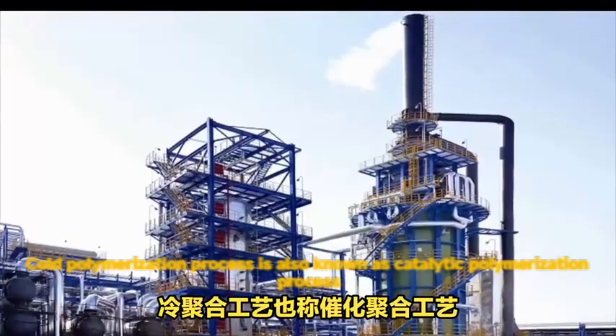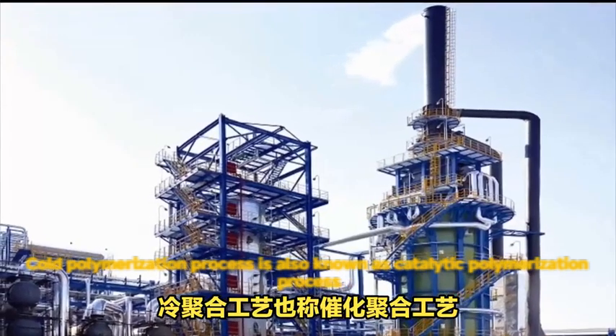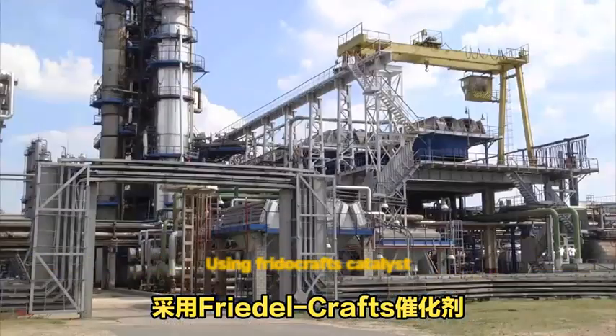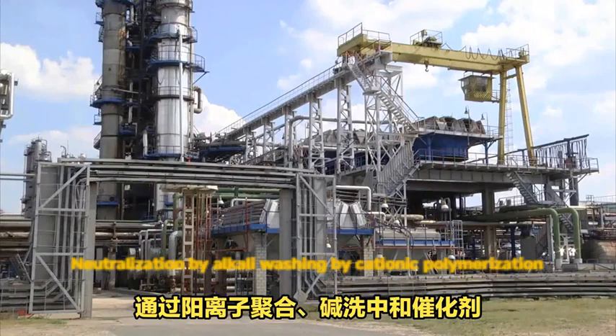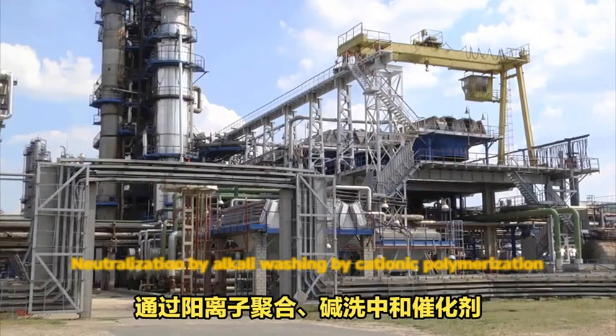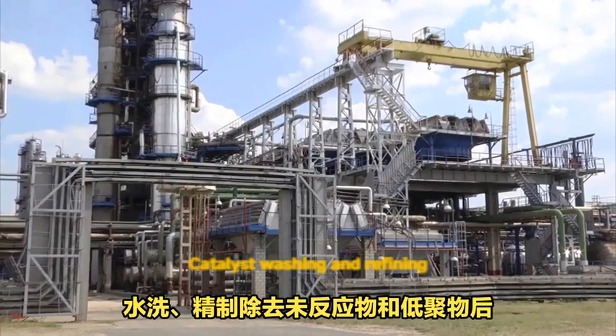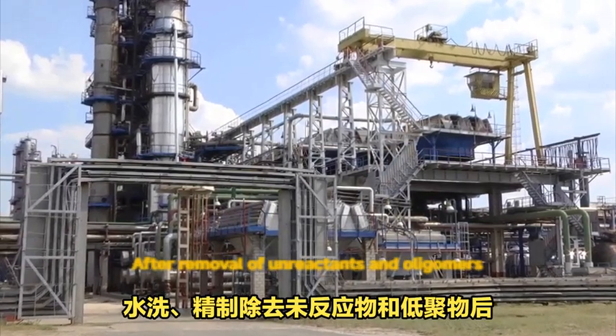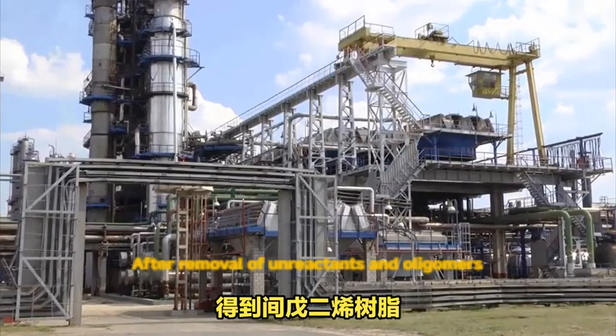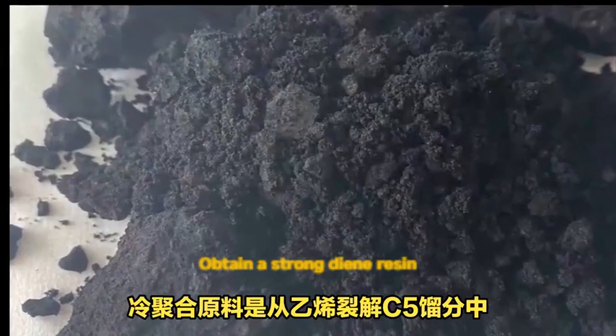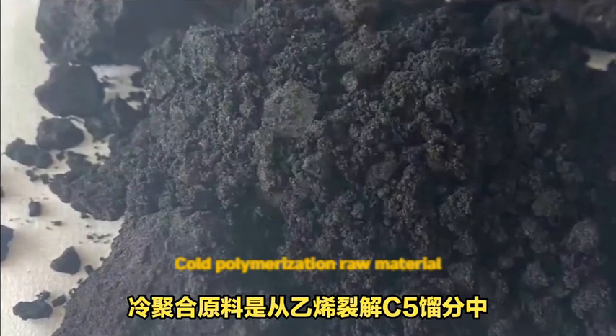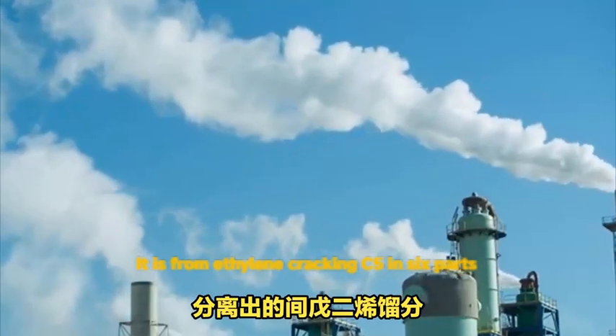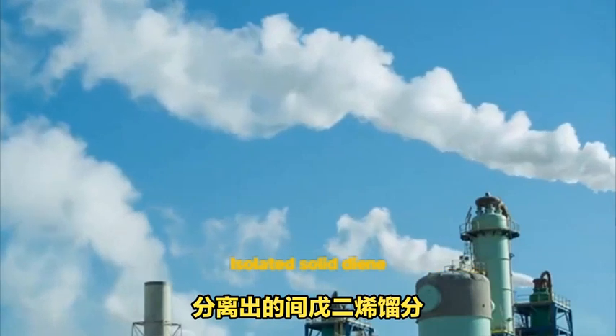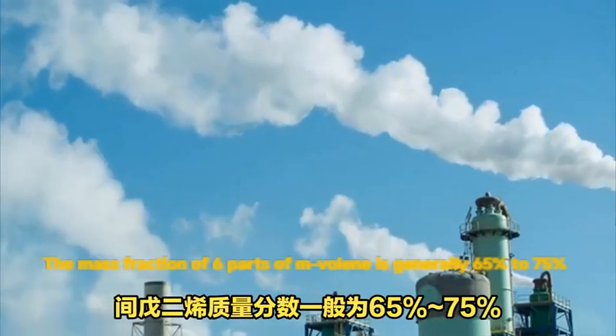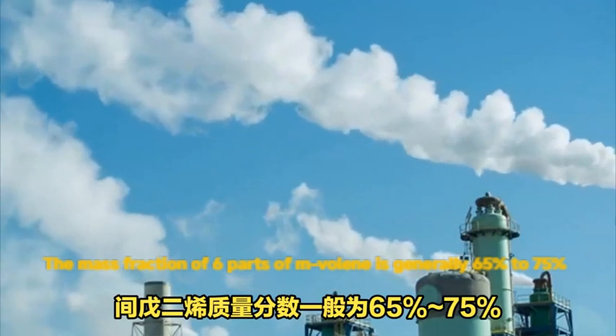The cold polymerization process is also known as the catalytic polymerization process, using a Friedel-Crafts catalyst. After neutralization by alkali washing following cationic polymerization, the catalyst is washed and refined. After removal of unreacted material and oligomers, a C5 resin is obtained. The cold polymerization raw material is the C5 fraction from ethylene cracking. The mass fraction of piperylene in the C5 fraction is generally 65% to 75%.